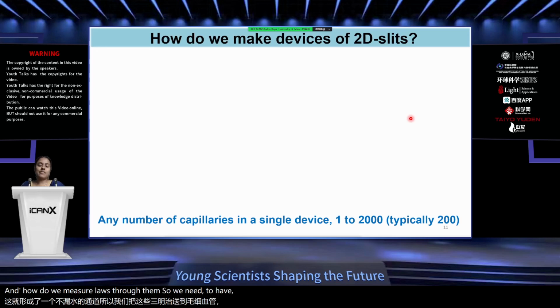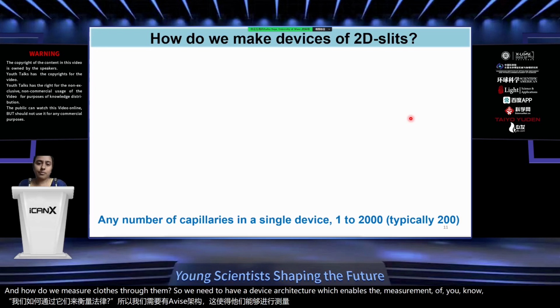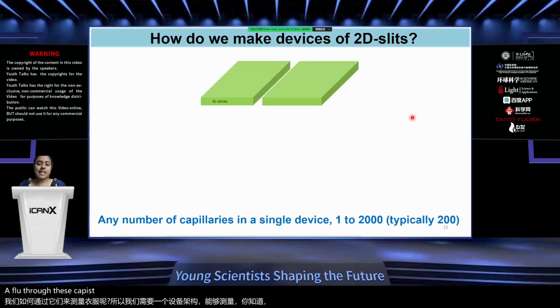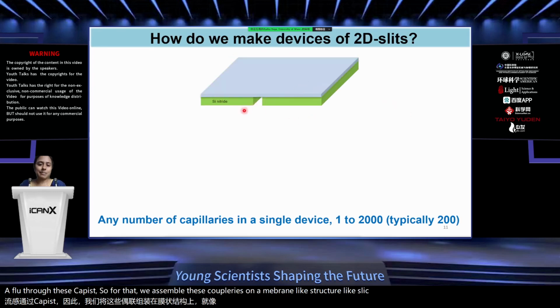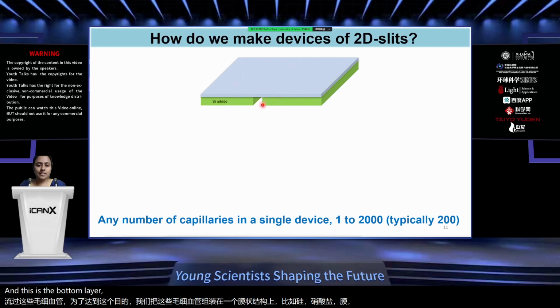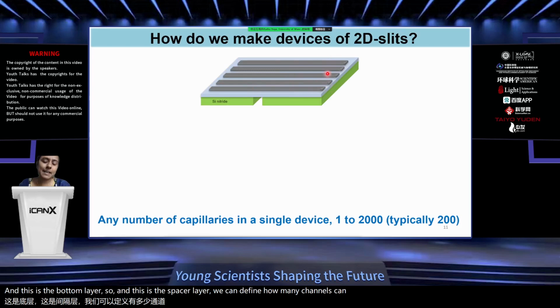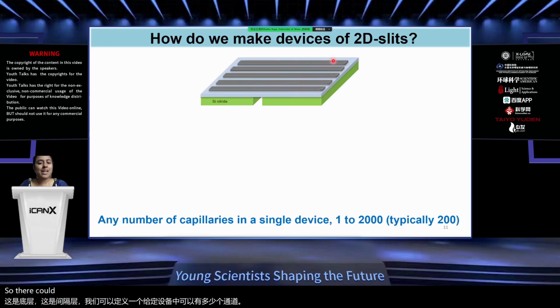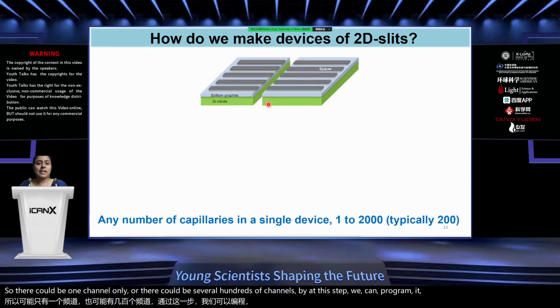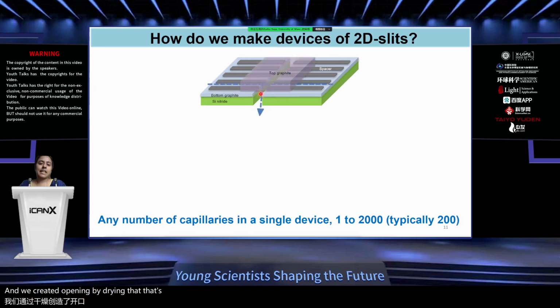So we need to have a device architecture which enables the measurement of flows through these capillaries. For that, we assemble these capillaries on a membrane-like structure, like silicon nitride membrane, and this is the bottom layer. And this is the spacer layer. We can define how many channels can be there in a given device. So there could be one channel only, or there could be several hundreds of channels. At this step, we can program it, and we create the opening by dry etching methods. And now we place the top layer.